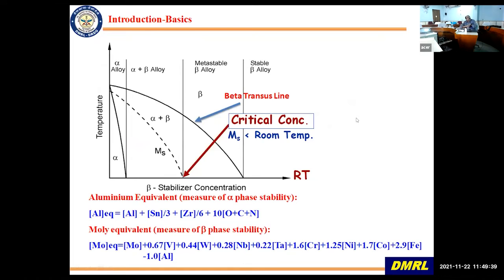Now here I'm showing you a pseudo-binary phase diagram. That is an imaginary diagram which has been drawn. Here on the y-axis you have temperature. On the x-axis you have beta stabilizer concentration. Now what is beta stabilizer concentration? It is basically calculated by this empirical formula, which is known as molybdenum equivalent, and it is a measure of beta phase stability. So the higher this number, the more the alloy is beta stabilized. You can see here all the beta stabilizing elements along with their multiplying factors have been put in. So you can put in whichever elements are there in the alloy, multiply by the factors and get a number. So that is what is plotted here, beta stabilizer concentration.